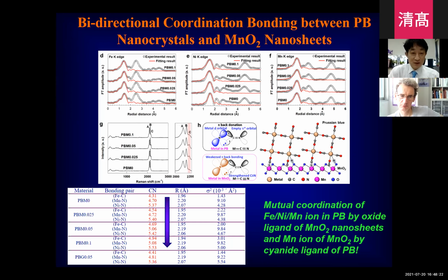Also, we use the Raman. The peak here corresponds to the cyanide ligand. But if you replace the metal ion with the manganese oxide nanosheet, the interaction between the manganese oxide nanosheet and cyanide becomes weakened. So it leads to the reinforcement of the cyanide bonding. It is related to the change of the pi back donation. As a result, we can observe the strengthening of the CN bonding, and so the higher energy Raman peaks. This is the evidence for the coordination bonding between cyanide and the manganese ion in manganese oxide nanosheets. So by combining the XAS and Raman, we can confirm the formation of the bidirectional coordination bonding between Prussian blue and the manganese oxide nanosheet.